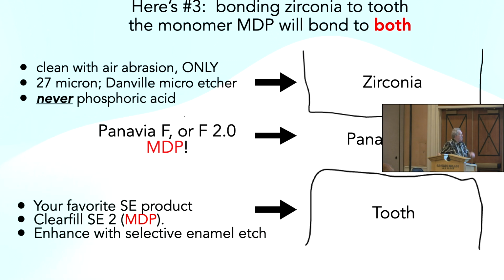The way you treat the zirconia is to air abrade it to clean it. You can use 27 micron aluminum oxide. Some of you are familiar with a lab study where they sandblasted with a 100 micron particle at 150 psi, and then they had fractures in the ceramic. Well, none of us are using that kind of pressure and particle size clinically. If you're using 27 micron at 30 to 50 psi, you're cleaning and not microfracturing, so don't worry about it.